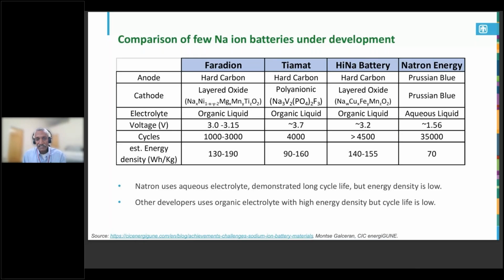But if you look at the cycle life, they showed very large cycle life. Natron's Prussian blue analogs have 3D structures with large, let's say, cavities for the transport in and out of sodium ions. Because of that, it puts less stress on the material. It has a large cycle life. Go to the next slide.